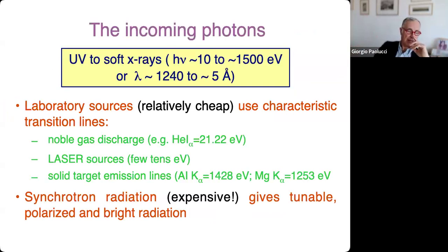So the wavelength we're talking about is from 1240 to about 5 angstrom, which corresponds to a photon energy of 10 to about 1500. Actually, nowadays people tend to go above 1500 electron volts. You can use laboratory sources which are basically using something related to the properties of a material. So, for example, you use helium-1 alpha radiation, which is 21.22 eV, and that's it. Or you can use aluminum K alpha or magnesium K alpha radiation, which are also fixed in energy because they are based on the K alpha emission.